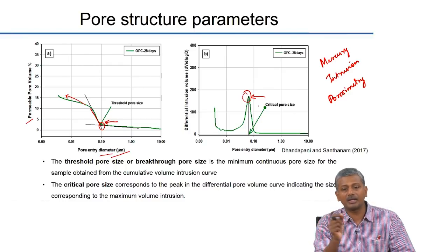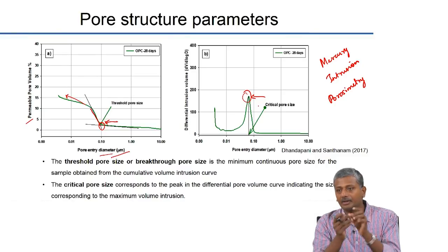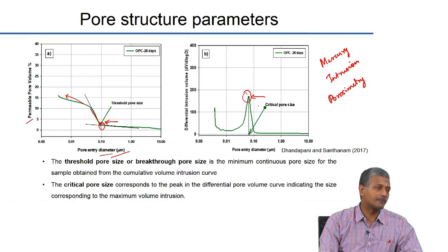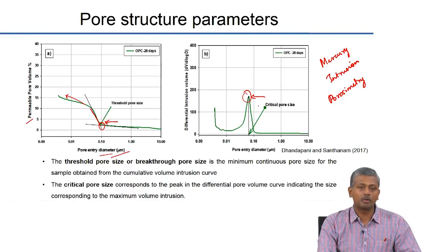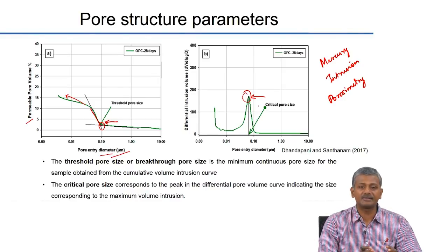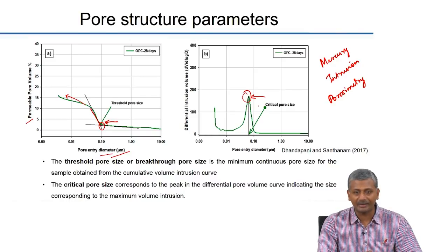You will not be able to take the mortar and aggregate interface, because the size of the sample is restricted. So, studying ITZ with MIP may not be possible at all, unless you are talking about the ITZ that exists between cement paste and fine aggregate. The coarse aggregate ITZ is simply not going to be determined by MIP.